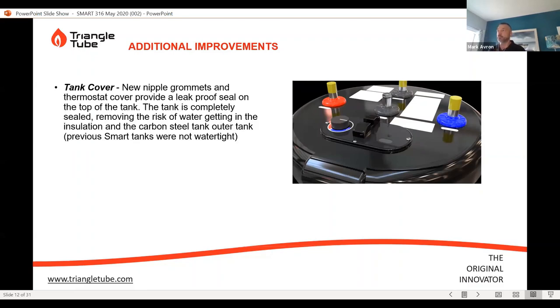Other improvements: we talked about the top of the tank. Those of you that have been familiar with the Smart Tank for a lot of years, there was a time where we used to ship the tank with a float vent on the top. The outer tank is effectively boiler water, and in order to get the air out of that tank, we've got to have a way to purge it. In the past, we'd use a float vent, and over time that float vent could leak if it was not maintained, and those leaks on the top of the tank could eventually make their way into the foam insulation, and eventually onto the carbon steel, and rot the tank out.